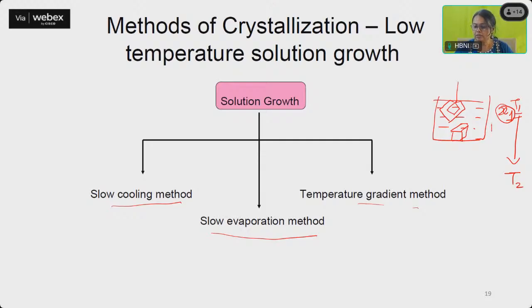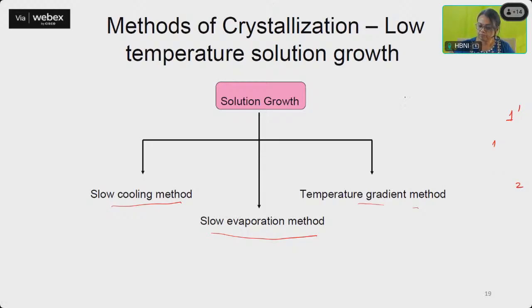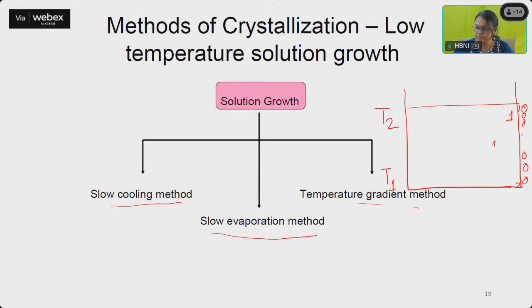Or very similar to this, we can have a temperature gradient method. Here we are maintaining T2 temperature and here we are maintaining T1 temperature. So in the same system, we are maintaining two temperatures. At the top I am maintaining a lower temperature and below I am maintaining a higher one using some heater coils. My seed is here. Initially I am putting the material below, because more will be dissolved there, and then I am stirring it. Some material will go to the top, and because the temperature is lower there, it will start to condense and the crystal growth is happening. So this is the temperature gradient method.